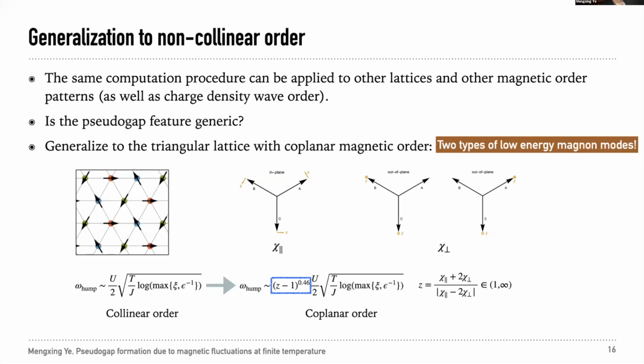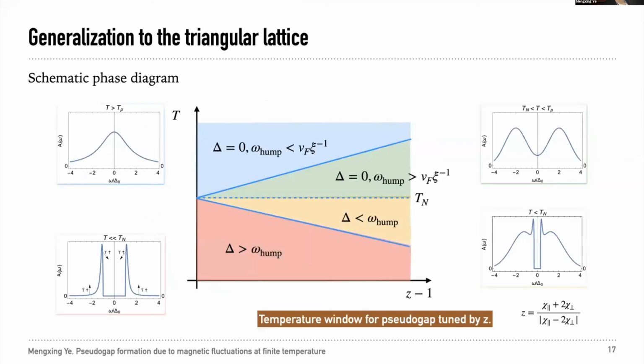And this z can vary from 1 to infinity. Because of this, we can get the phase diagram as z varies. I want to emphasize here that following the same procedure, we find that when z equals 1, there is no pseudo gap behavior. And by varying z, we can vary the temperature range for this pseudo gap physics.